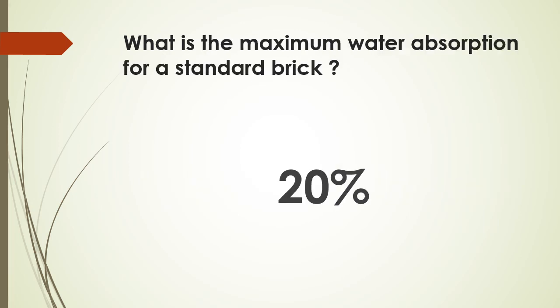Next is water absorption for a standard brick. When a brick is immersed in water for 24 to 48 hours, after removal, more than 20% of water must not be absorbed by the brick. If it absorbs more than 20%, it is not recommended for construction. The water absorption ratio must not cross 20%.